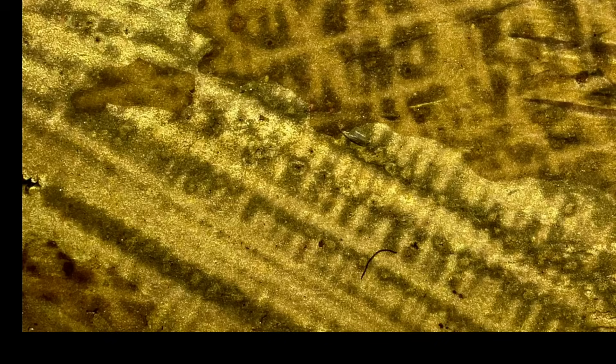So eventually we reach a point where the bulk liquid which is now enriched in zinc is going to completely solidify. And now we can take advantage of this zinc concentration gradient by etching the material. Ferric chloride will preferentially attack brass with more zinc in it. So the interdendritic regions are going to be etched much faster than the dendrites themselves. But the dendrites will still be etched especially the outer layers because remember the core is the highest in copper and it decreases from there. This is why the dendrites look kind of blurry and not completely sharp interfaces. So thanks for sticking around for this long-winded explanation but let's get back to the material.